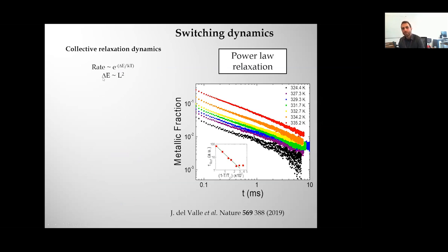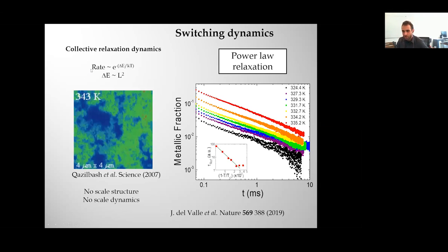So when you have systems with strain, which is where you observe this power law relaxation dynamics, what strain does is that it couples together larger areas. So to flip these larger areas will cost you much more energy, and that's why you will have different relaxation rates. So let me show you, this is the distribution of metallic and insulating domains taken from this